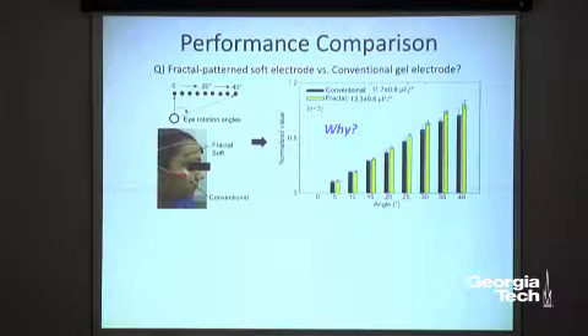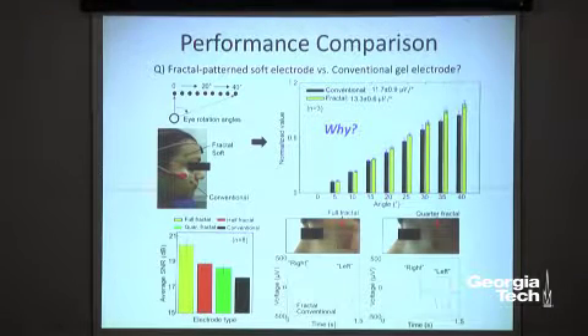It's very interesting, right? So we checked why. And we found out that, when you look at this electrode over here, we designed our electrode by following the size of the conventional one, which is about 1 centimeter square, right? But the thing is, if you look at this conventional one, they are using the metal and the gel. Again, the metal and the wire are heavy. So they have to use this tape, right? They have to use some of this area to put this onto the skin.